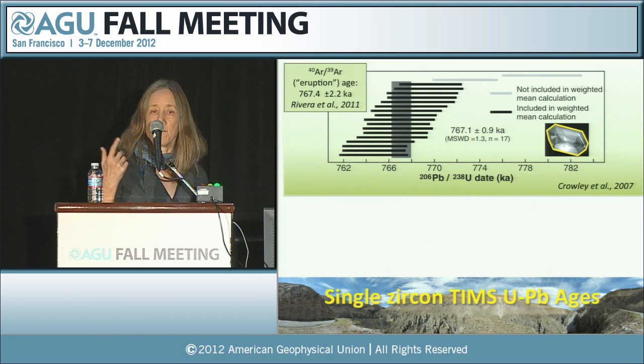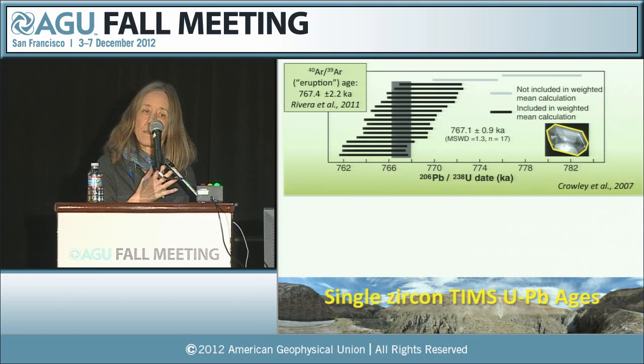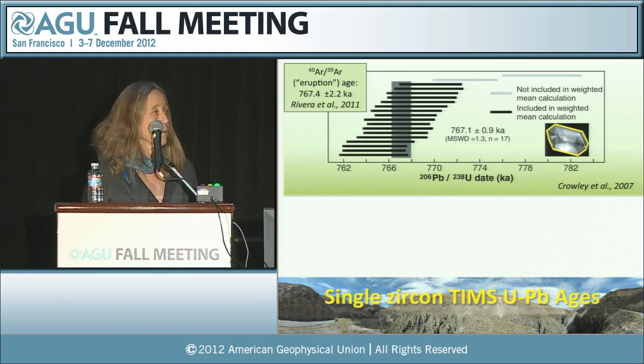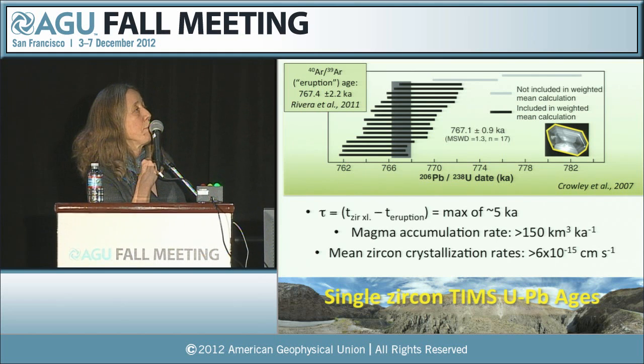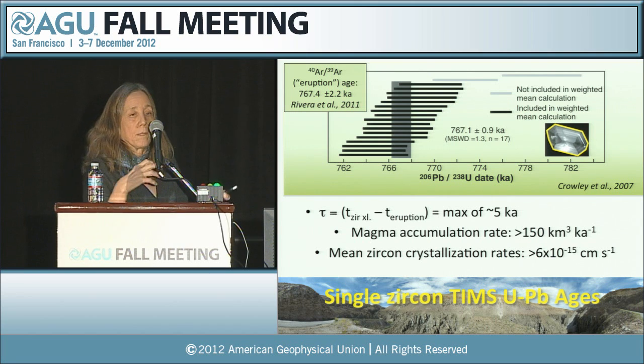And interestingly enough, Fidel brought up the fact that we often see a difference between the timescales of major phases and minor phases, accessory phases, and this doesn't seem to be the case based on these data. So I'm going to refer in the rest of my talk to this tau, which is just the difference between the time of zircon crystallization as determined from the geochronology and the time of eruption, and allowing for all of the various kinds of uncertainties that come into play here. You might be able to imagine a maximum of 5,000 years for crystallization of the zircon crystals from the Bishop Tuff melts. From that, of course, we can determine a rate of magma accumulation, assuming this is giving us some idea about how long it took to get the magma together, and a mean zircon crystallization rate.